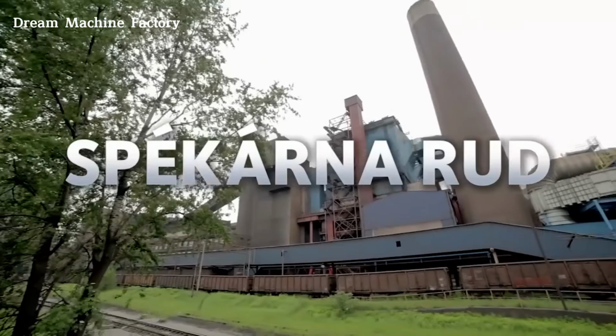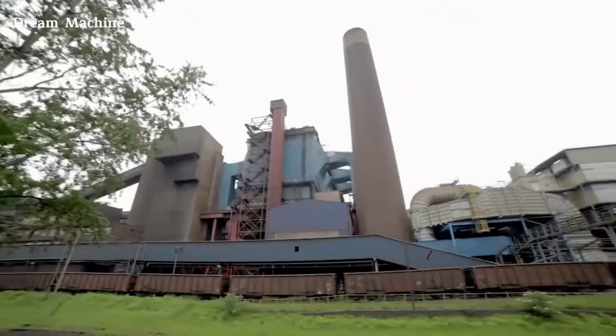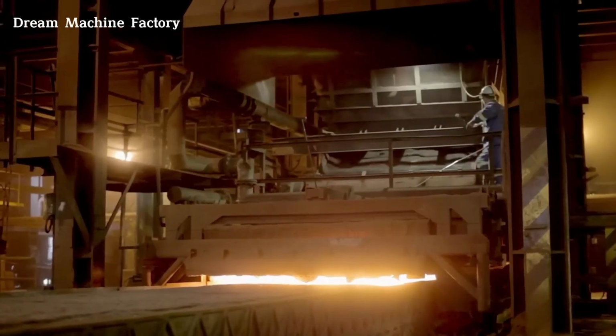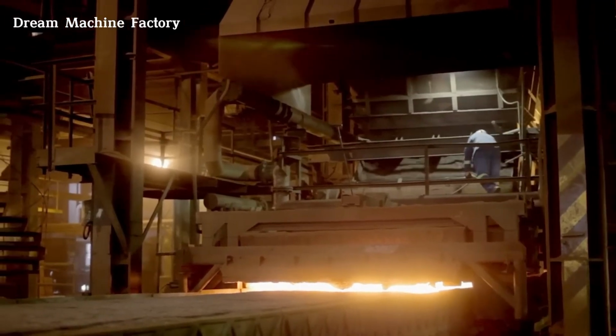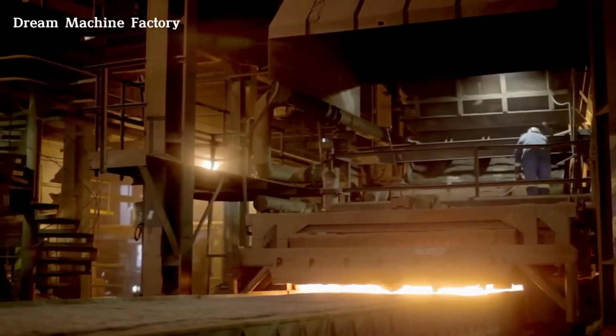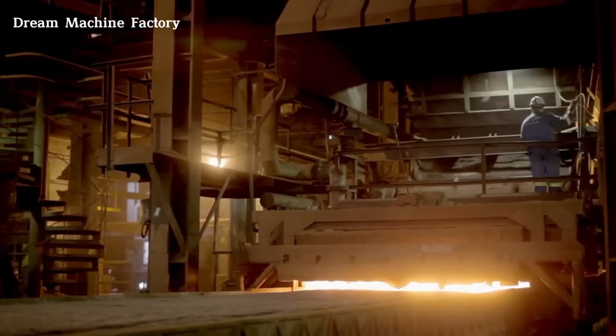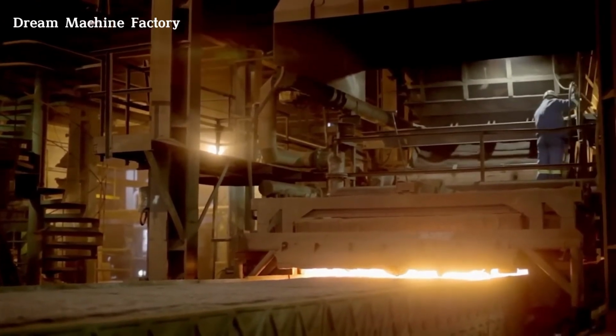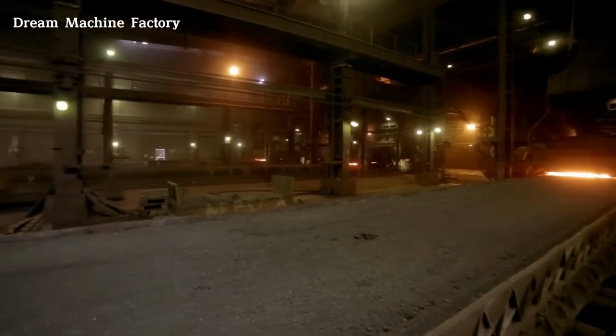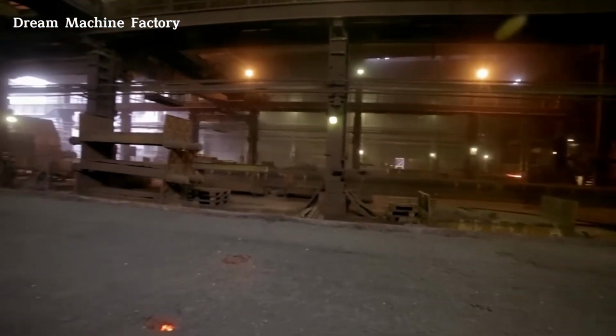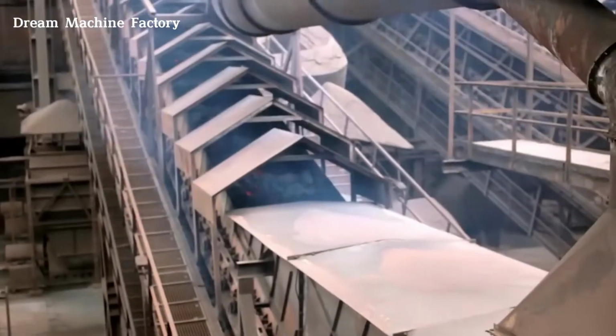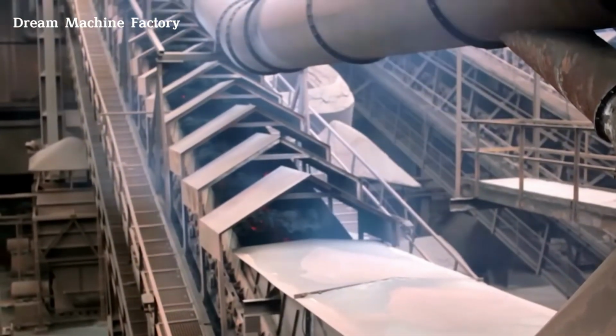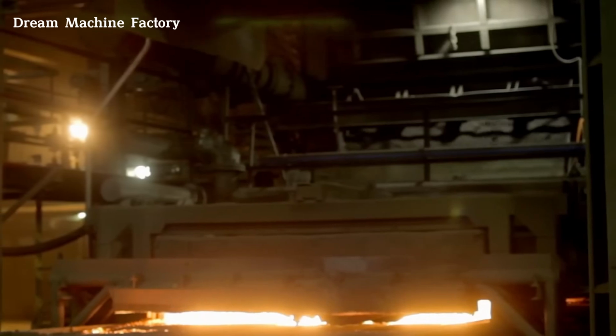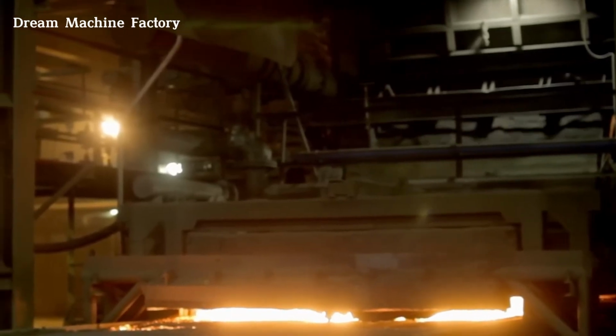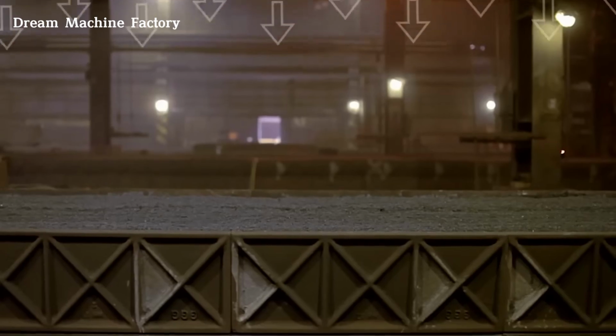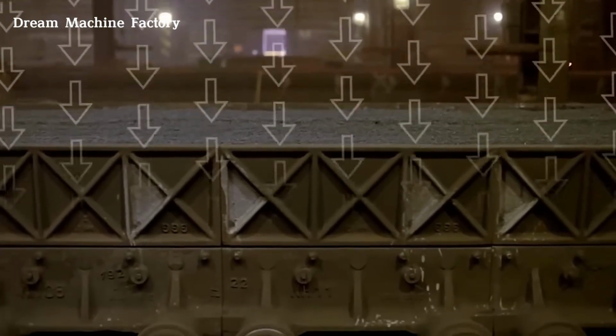The ore sintering plant, also known as the sintering unit, plays a critical role in preparing iron ore for the blast furnace. Here, fine iron ore dust, coke breeze, a byproduct of coke production, limestone, and other additives are blended with water to form a mixture called the sinter feed. This mixture is loaded onto a moving grate sintering belt, ignited at the top, and air is drawn downward to heat and partially melt the material. The result is sinter, strong, porous clumps that improve furnace permeability and fuel efficiency.